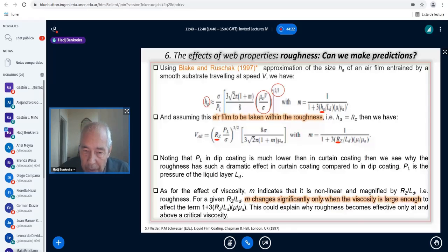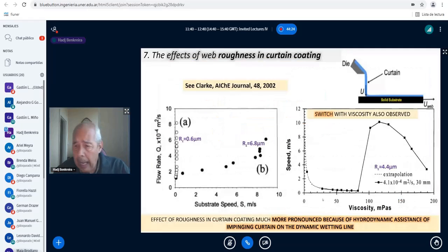And actually we observe the same thing in curtain coating. If you look at the work of Clark later on, he also observed that with curtain coating there is a switch where these phenomena happen. And of course in curtain coating the gain is much higher because you have hydrodynamic assistance.